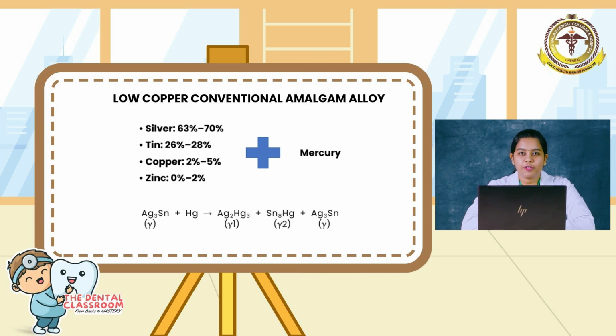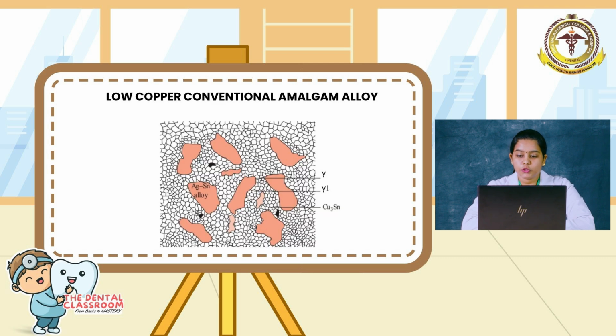These components of alloy powder, when mixed with mercury, form the gamma 1 phase, gamma 2 phase, and gamma phase. The picture on the right side shows the microstructure of set low copper amalgam. The set amalgam consists of a core of unreacted gamma alloy particles surrounded by gamma 1 and gamma 2 phase.